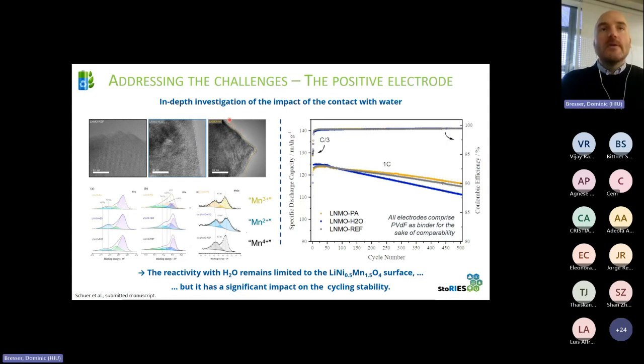In the case of the phosphoric acid, what probably happens first, due to the greater reactivity, is that the phosphoric acid reacts with the lithium transition metal oxide, forming a thin layer of probably predominantly lithium phosphate, potentially also some manganese phosphate, and to a lesser extent nickel phosphate here at the surface. And this metal phosphate layer then stabilizes the interface, right? And so this is then shown here in yellow. So when you use aqueous phosphoric acid instead of water, you still have a reaction, but this reaction has a positive impact on the cycling stability.